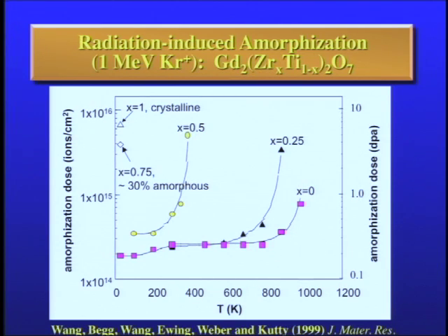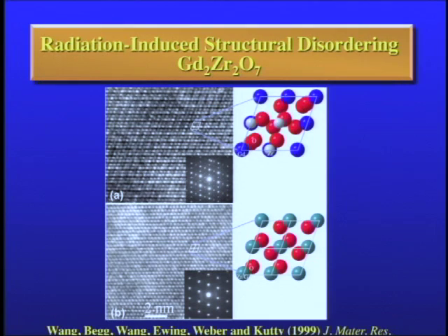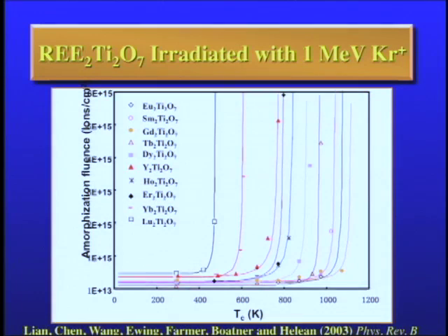And when I say no longer amorphize it, that's up to over 100 dPa. And for comparison, zircon becomes fully amorphous at about 0.2 dPa. So these are very radiation-resistant materials. And what's happening, and we can see it in the high-resolution electron microscopy, is you start with pyrochlore, and then you simply disorder, and as long as it's zirconium mainly instead of the titanium, you always go back to the defect fluorite structure, and the material remains crystalline.